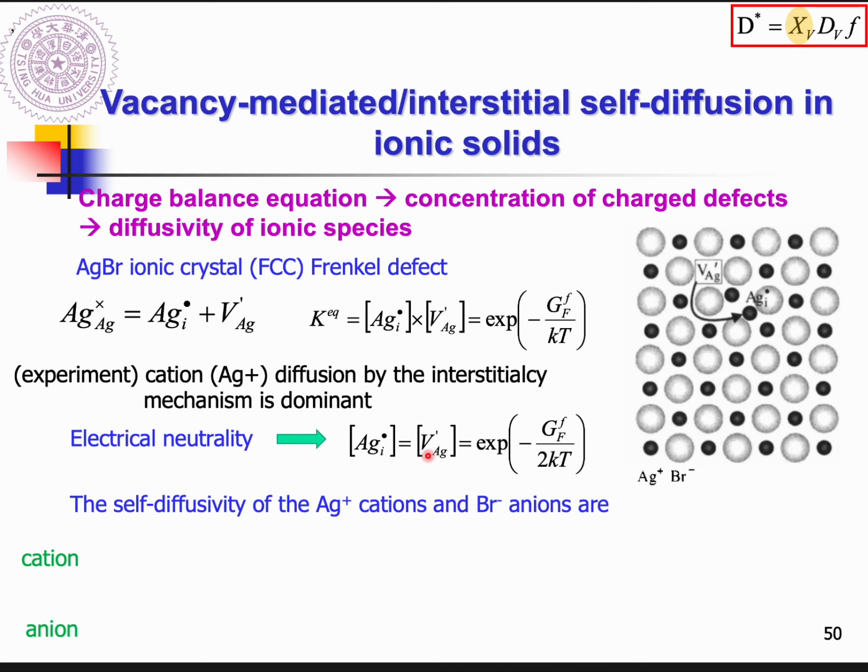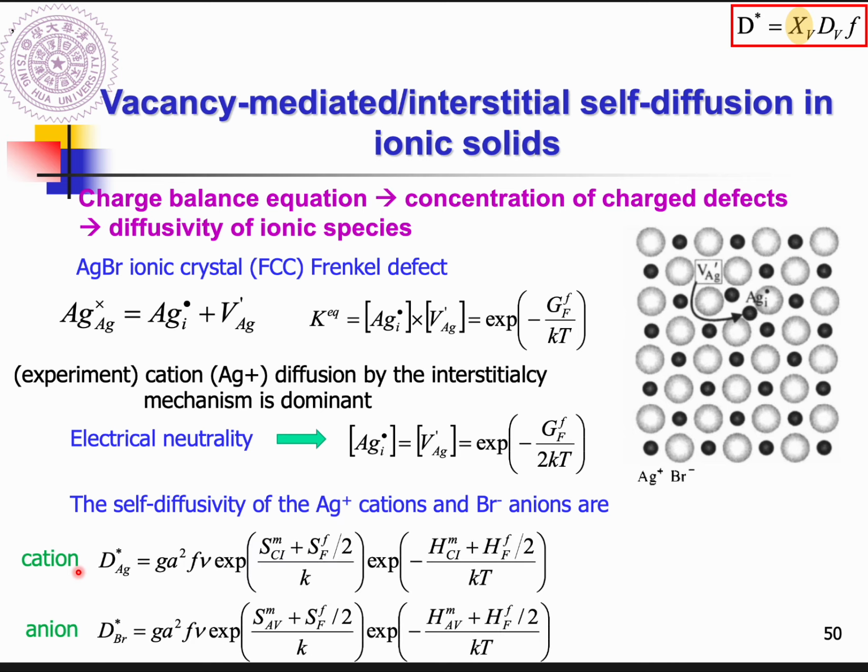So we get the fraction for this one and this one equals exponential of minus Frenkel defect formation energy divided by 2kT.